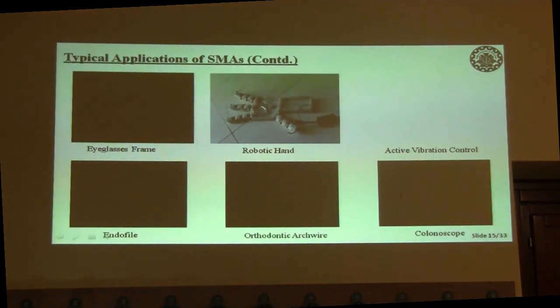Here you can see a very flexible eyeglass frame. This is not just due to ease of usage. This is due to the stress plateau. Since the temperature of our body is almost constant, for different sizes of a face in ordinary materials, by changing the applied strain, I will obtain different levels of stress. But with the use of shape memory alloy, since I mentioned that the level of stress is more related to the amount of temperature rather than strain, it causes to apply almost the same level of stress.